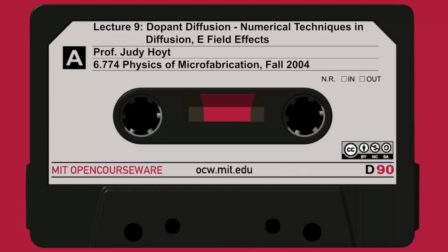Then you multiply and divide by delta x, and you end up with the equation that this flux is equal to, on the right-hand side, minus V b over 2 times delta x squared times delta C over delta x, something that's starting to look like a slope. So we immediately see some kind of Fick's law here, where a flux is related to a slope times something out in front that is a constant. So that's the bottom of slide 15.